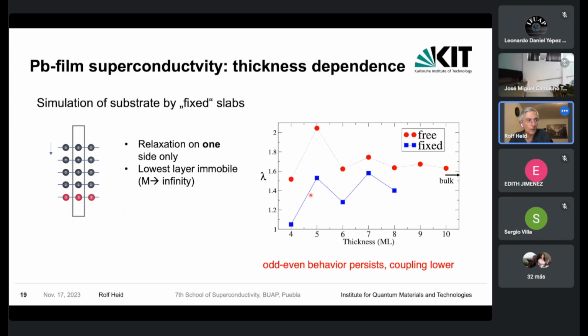And overall, one also sees that now there is a small trend of reduction of this coupling constant when going to thinner layers. So we believe that at least this neglect of the substrate seems to be one ingredient which is missing in the previous calculation, and which is therefore needed to understand the decay of Tc when going to thinner slabs.